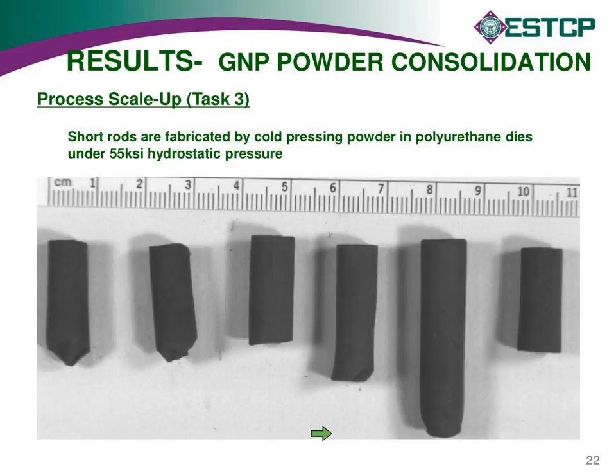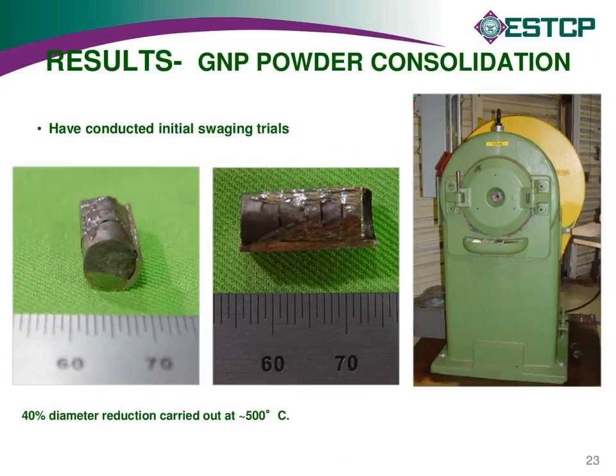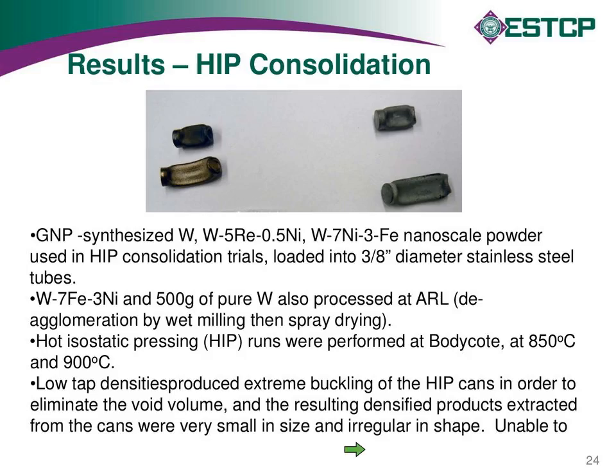Well, again, some other attempts with pressure. The big thing was trying different consolidation swaging approaches to consolidate this material before we enter the sintering process, to help things along. And then the other major work in terms of consolidation was looking at hot isostatic pressing. The problem we were having with these highly agglomerated powders is that when you fill the can, you end up with a material with a very low tap density, so a lot of void space. And when you HIP consolidate and the can crushes in, you end up with a highly deformed final can that is very difficult to get useful specimens out of.